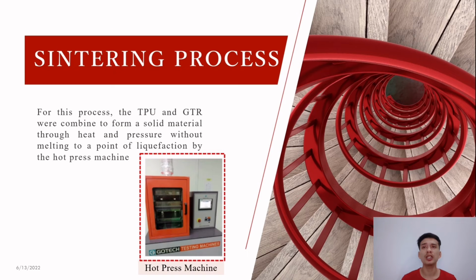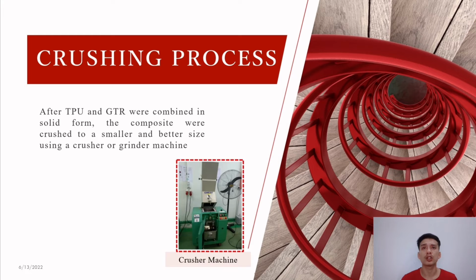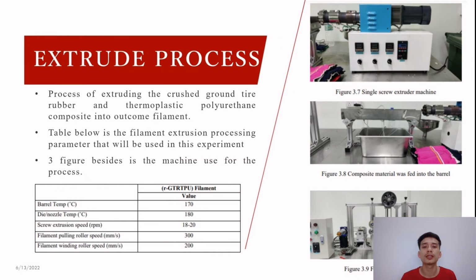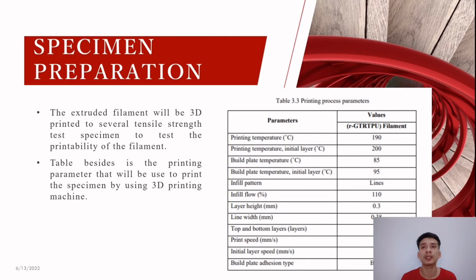For the sintering process, the TPU and GTR combine to form a solid material through heat and pressure, without melting to the point of liquefaction, using the hot press machine. For the crushing process, the composite is crushed to a smaller and better size using a crusher or grinder machine. For the extrusion process, the GTR and TPU are extruded into the outcome filament. The table below shows the filament extrusion processing parameters that I follow. The machines involved in this process are the single screw extruder, the barrel, and the filament storage rollers. Then we proceed to specimen preparation, where the filament is 3D printed into several tensile test specimens to test the printability of the filament. The table shows the printing parameters that we use.